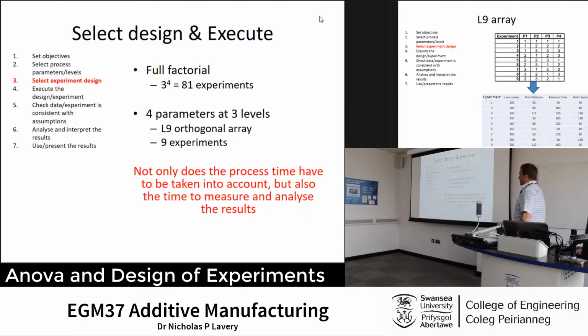So if we were to do a full factorial, with 3 levels and 4 parameters, 3 to the power 4 is 81 experiments. Now, if we have the same 4 parameters and 3 levels, and we use an L9 orthogonal array, we bring that down to 9 experiments. So it's a lot less work. Now, remember what I was saying, that repeatability is also important. So you wouldn't just do the 81 experiments once, because each of those individual combinations of parameters and levels would have to be repeated a minimum of 3 times to get a standard deviation. So you'd actually have to multiply the number of samples we made by 3, 3 times 81.